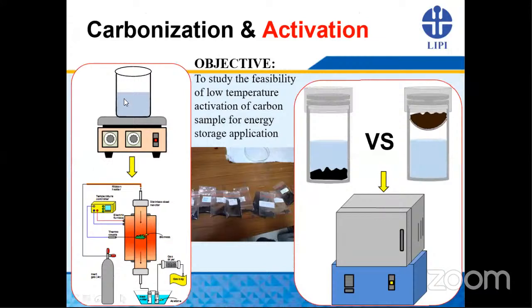So in here we carbonize the sample at first, carbonize the coffee waste sample, and then we get the carbon. After that, we try to study the feasibility of low temperature activation using this kind of autoclave solvothermal method. First, we compare when we put the carbon sample in the solvent, immerse the carbon in the solvent, and also we put the carbon sample here up above the solvent here.